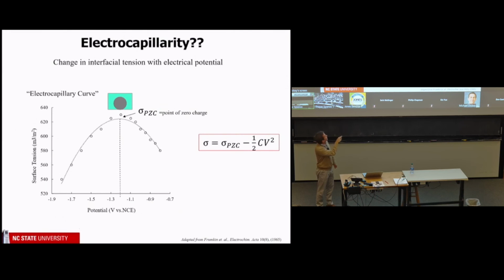So here we are, it hates its surroundings. And we can trick it into liking the water by applying a voltage. If we apply a positive or a negative voltage, it doesn't really matter, because you get the opposite ion coming to the interface, which are these red things. The equation that describes this is that the surface tension, which is what we're plotting, is the value at the point of zero charge, PZC, which is here, minus 1/2 CV squared.